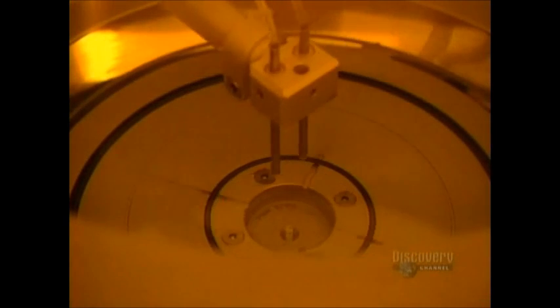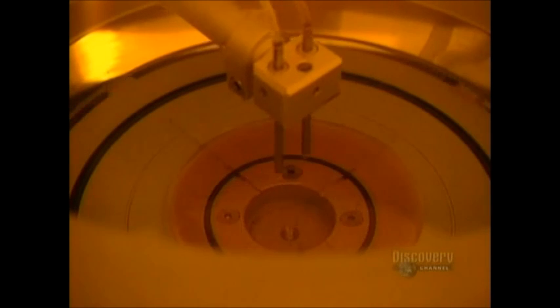At this stage, two chemicals are applied: a primer and a photoresist coating. This operation is done at a temperature of 21 degrees centigrade and lasts three minutes.